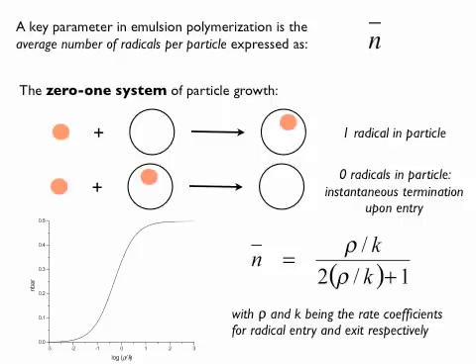A little bit later in time, a second radical wants to do the same thing. That other radical already in there is happily propagating, becoming longer and longer. The second one comes in, but it's a relatively short molecule. Radical termination in free radical polymerization is diffusion controlled, so when that small radical comes in it might find the other one instantaneously and terminate. You have zero radicals as a result. So you either have one or you have zero — statistically over time it cycles zero, one, one, zero. The average, by definition, is a half. So in zero-one kinetics, n-bar is 0.5.